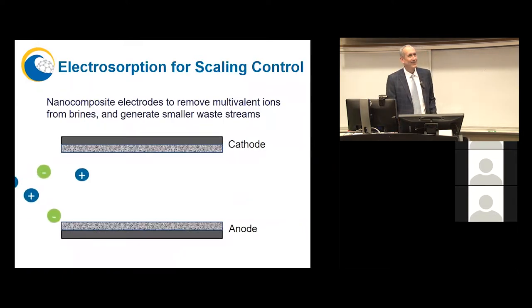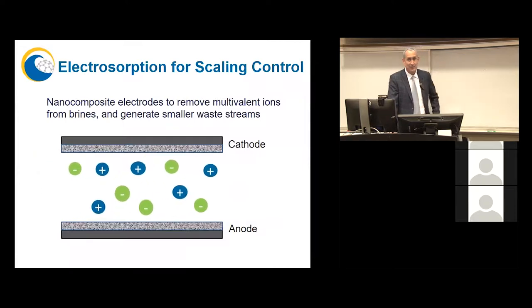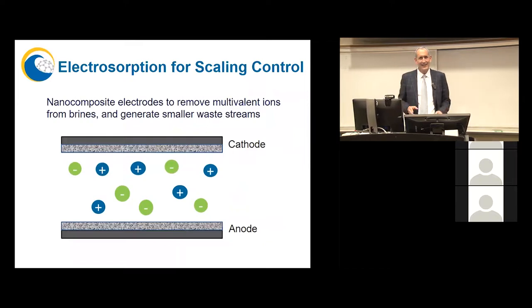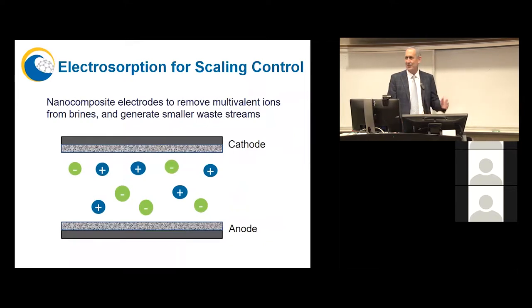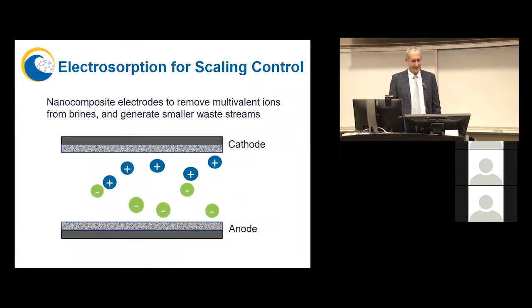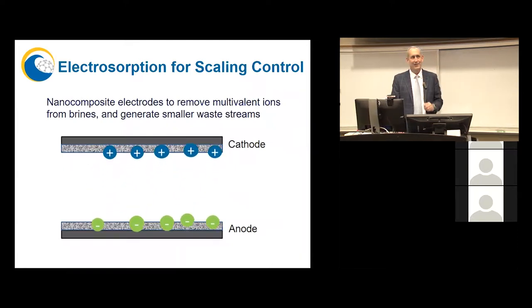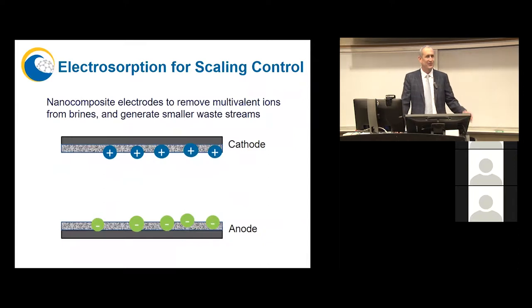Now, along the lines of low energy desalination, we have something called capacitive deionization that has been around for a while, at least 10 years. The general idea is to use electrodes that are charged to separate cations like sodium from anions like chloride. And it works okay, but it has a problem. The absorption capacity gets very easily saturated, and you can only treat briny water of up to 8,000 milligrams per liter of TDS. You can certainly not treat seawater with this.